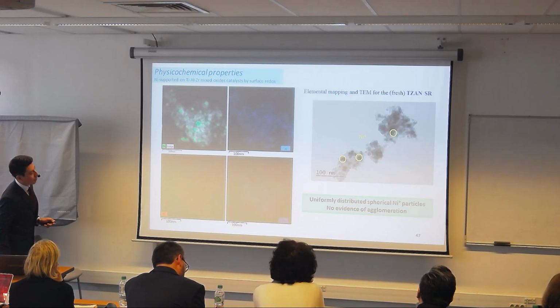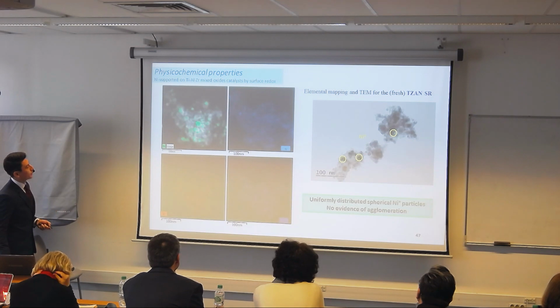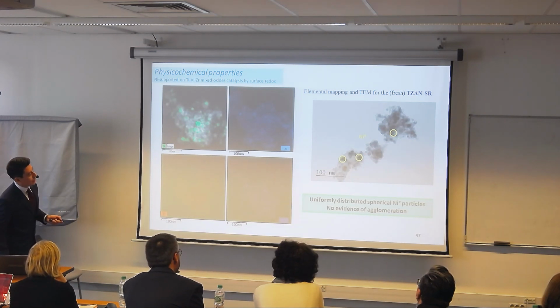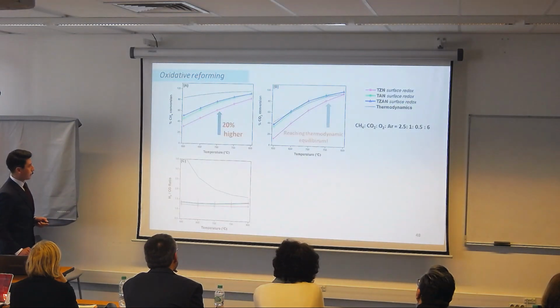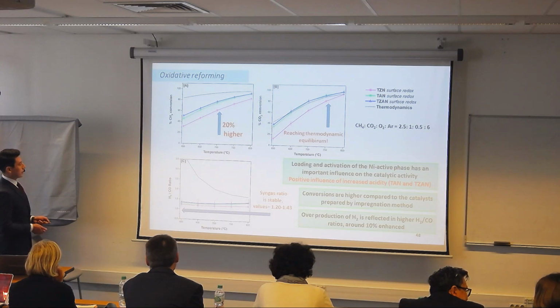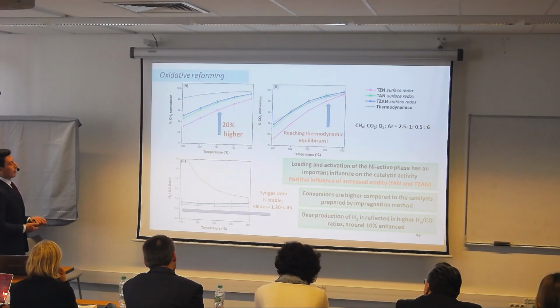After the synthesis, we can also validate the good distribution of the nickel on the surface of the support. As a sample, I have here this catalyst. You can see the support and the surface. We tested it, and we find even higher conversion compared to the others, about 20% higher. Finally, we are reaching the thermodynamic equilibrium with this catalyst, and the good thing is that we are stabilizing all the values through time at a syngas ratio between 1 and 1.43. So the loading and activation of the nickel active phase has an important influence, as we can see. The conversions are higher compared to the other catalysts prepared by impregnation.